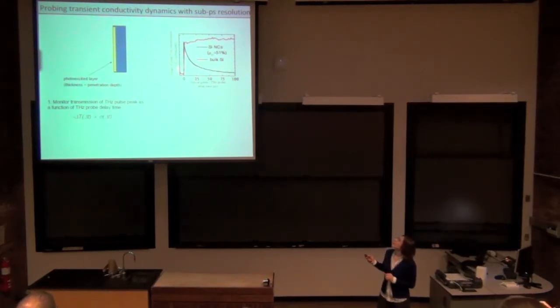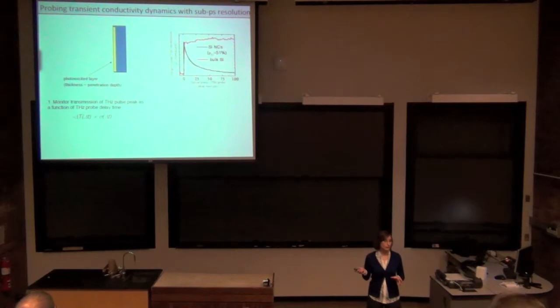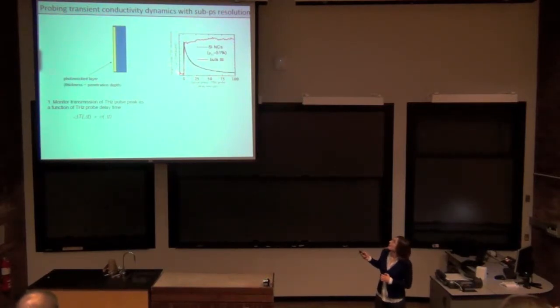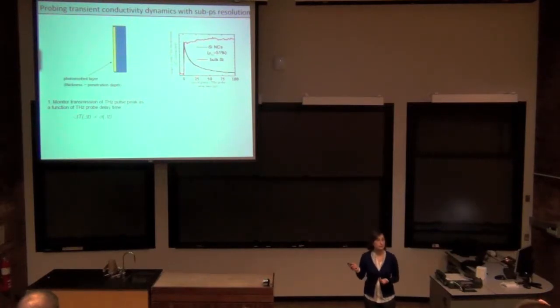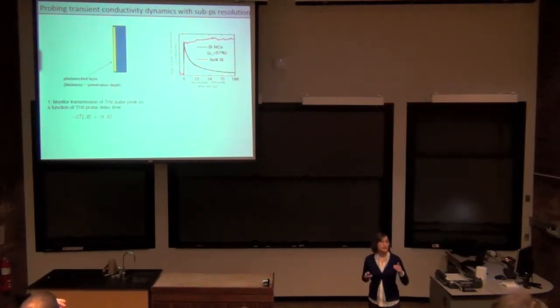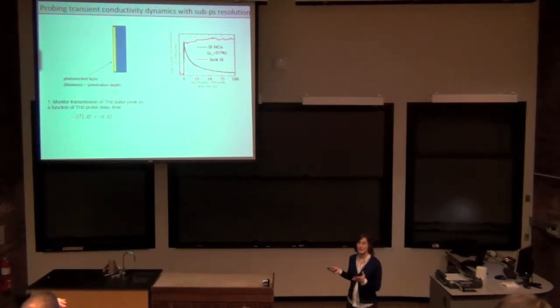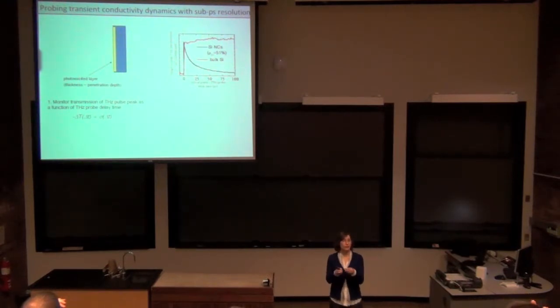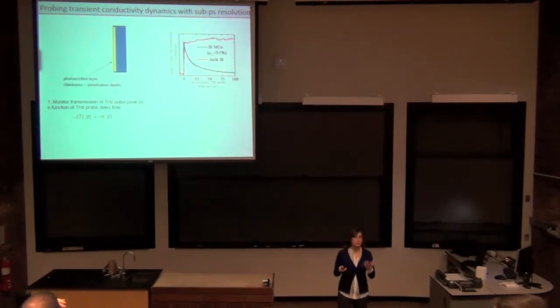So here's just an example. The red is for the bulk silicon wafer. What happens is the excitation comes in there, and the conductivity shoots up. Of course, you excited additional carriers. It stays on for a long time. Then in one of the silicon nanocrystal films, what we see is it goes up, and then within the first 100 picoseconds, it dies. That immediately tells us that all the carriers that we have excited have somehow gone to some sort of defect, trap states, surface states, or something like that. So of course, we directly extract the lifetimes out of this.